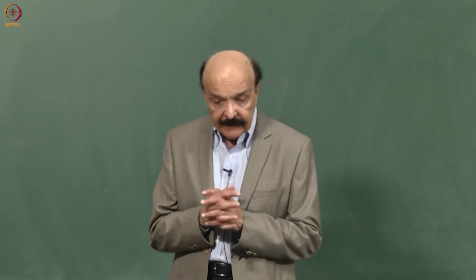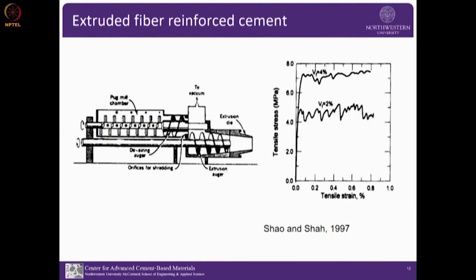Well, the third way is extrusion, and I talk about extrusion because it is a precursor to 3D printing, and we developed this in 1997. So this is a screw type extrusion. You have fiber reinforcement, material looks like a dough, and you push it through a die, and depending upon the shape of the die. And the fibers we used here are what I call microfibers. So they were PVA fibers, 14 micron in diameter, and rather short, 2 millimeter long.